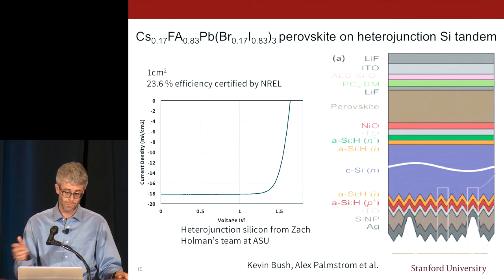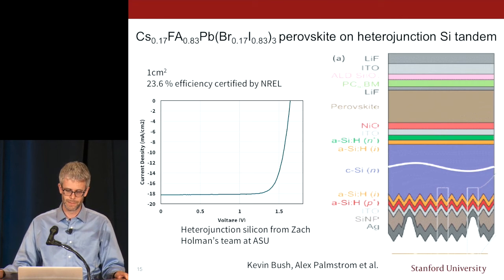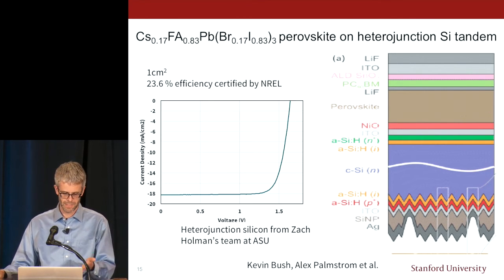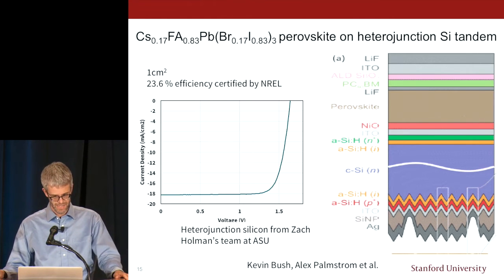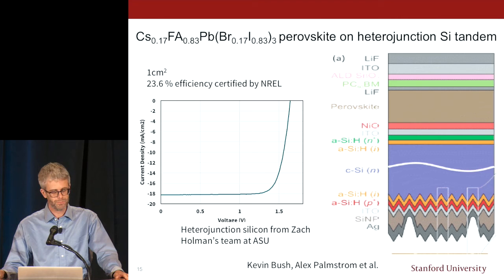And we got this working remarkably quickly, did not have to make hundreds of tandems to get this NREL certified 23.6 world record. And I will say in the last couple months, we've developed 5 improvements. We usually isolate the improvement. We don't, on a daily basis, make the entire stack. And when we do the next generation, it's going to be about 26 or 27% efficient. So really excited about that. And at that point, we truly will have upgraded the world record silicon solar cell.